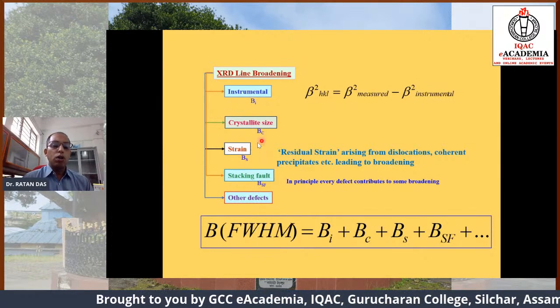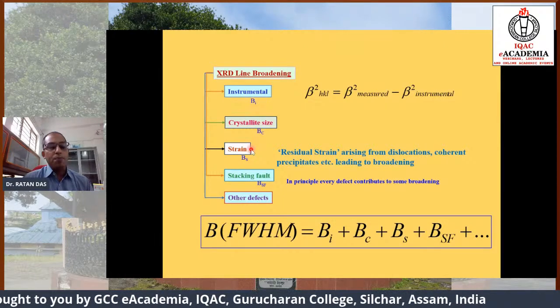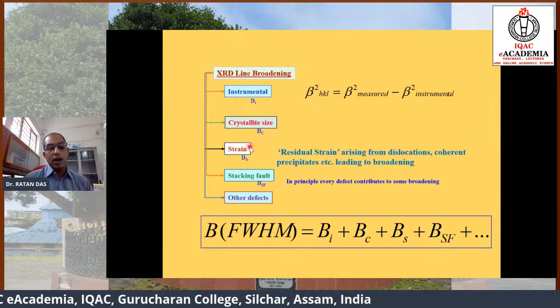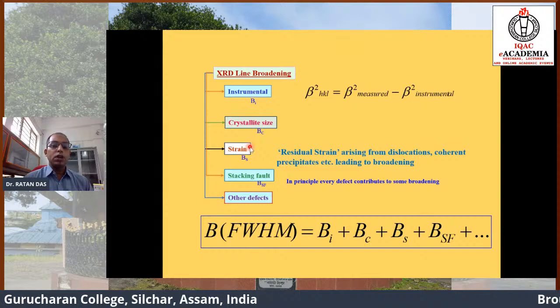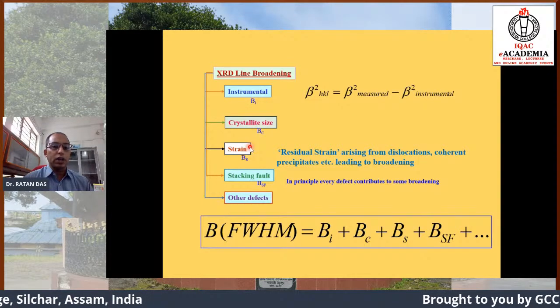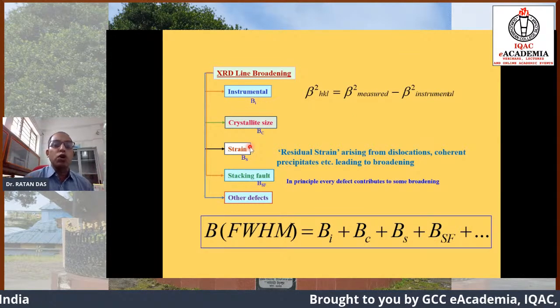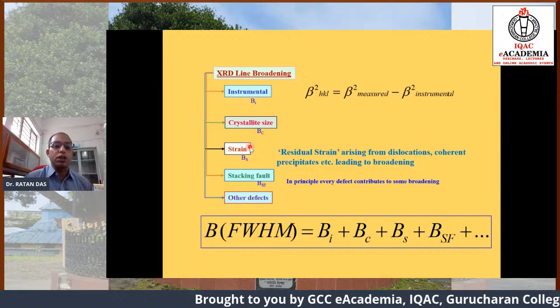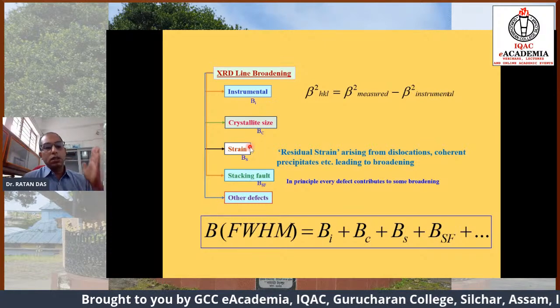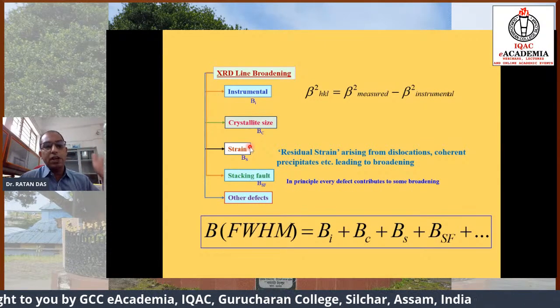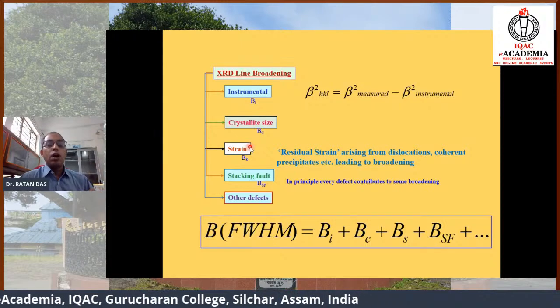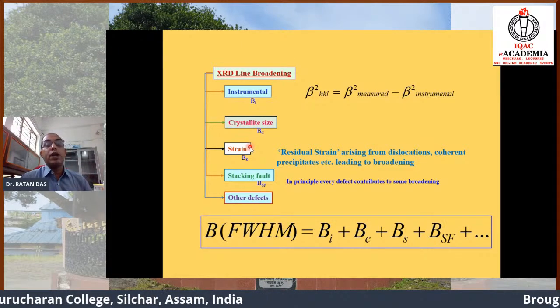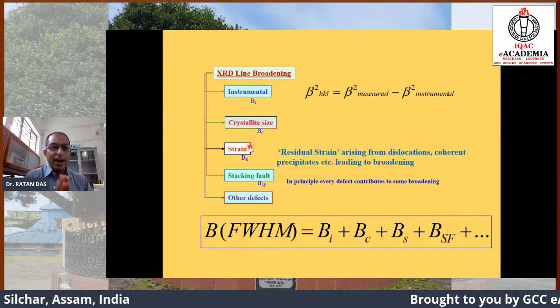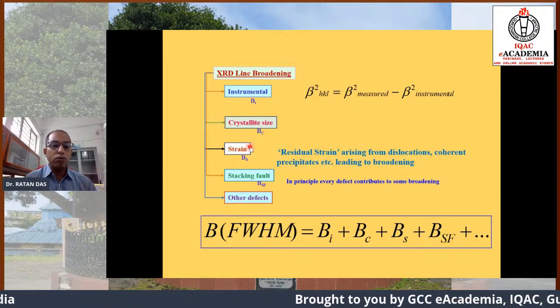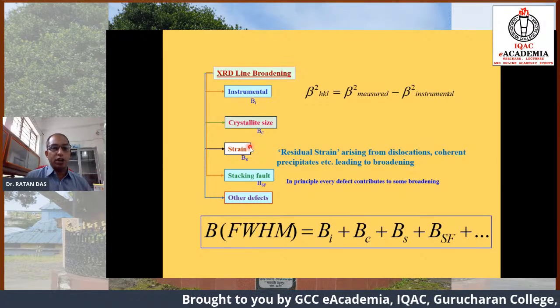So all the factors are coming into the picture, but the bigger role is played by the size and the strain in the X-ray diffraction line broadening. So the term is very important: X-ray diffraction line broadening. Line broadening means the infinitely peaked X-ray diffraction pattern in the case of a bulk sample gets broadened when we decrease the size to the nano range.